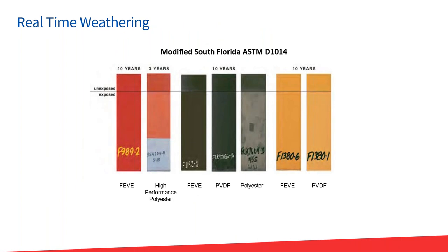Here's some panels for a more visual impact instead of just the graphical way of looking at degradation. You could see at the top above that black line is the unexposed. So these were areas of the panel that were covered, and then the remainder of the panel was just exposed to the sunlight. And so what you're seeing is not only that the fluoropolymer systems, both FEVE and PVDF, perform very, very well. They perform well with what look to be more organic type pigments.